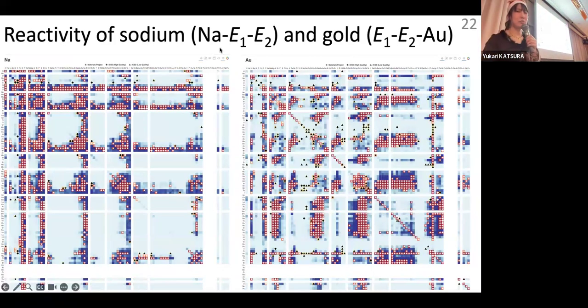So you may think sodium is a very reactive element. But when I plot this, there is plenty of white space. So sodium is not reacting with many combinations of elements. This matches with my experience that when we try to synthesize ternary compounds, sodium doesn't react. And my collaborating researcher is using sodium as a crystal growth flux. So that means sodium is not reacting.